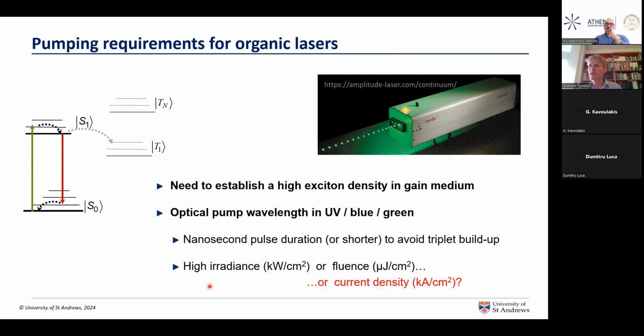This means that we need to work with very high irradiance. So I will often talk about the laser threshold, the pumping requirements to get the laser to switch on, in terms of kilowatts per square centimeter or watts per square centimeter, or sometimes in terms of microjoules per square centimeter. Or if we're electrically driving, then we need to look at the possibility of a current density to achieve this high excitation density in the film.